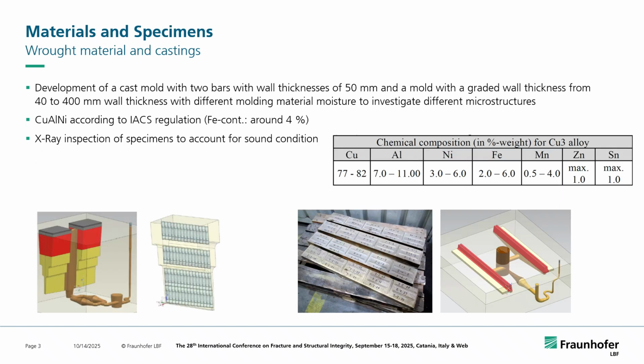In the next steps, I want to talk about the materials and the specimens, the wrought material that we cast from our project partner, which was MMG in Eastern Germany. They developed two different styles and designs of a mold. On the one side, we had something like a molding design with 2 bars where we removed the main batch of specimens having a wall thickness of 50 millimeters. You see here the casting system, the runners and the gate, the cut on both sides, and at the end these light yellow blocks and bars here were taken for the manufacturing of the specimens.